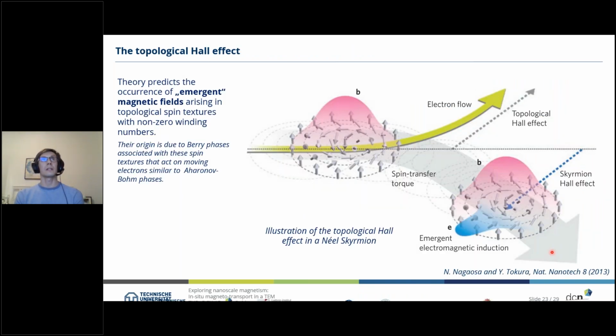In the literature, this is said to be the so-called topological Hall effect. The theory predicts the occurrence of emergent magnetic fields from these skyrmions, from these topological spin textures with non-zero winding numbers. This is shown here in this sketch: if you have a skyrmion, in this example, and an electron flowing through, you have an additional component of deflection by that topological spin texture on the electron flow. This is called the topological Hall effect, which comes in addition to the already existing anomalous Hall effect.